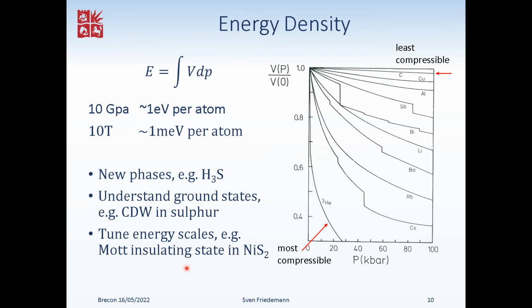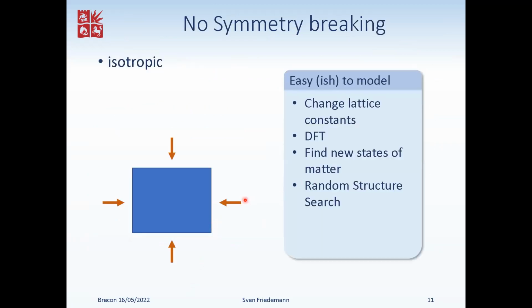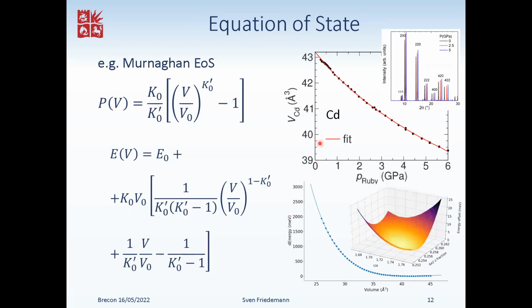One other important property of high pressures is that if we do indeed manage to have hydrostatic conditions, it's isotropic, and hence it's reasonably easy to model this in theoretical or ab initio work, namely by simply changing the lattice constant. I showed yesterday some DFT results that we've obtained on titanium selenide, but a lot of the community uses this to find new structures, to predict new structures and evaluate which ones could be interesting, for instance, for high temperature superconductivity. A key piece in this is the equation of state.